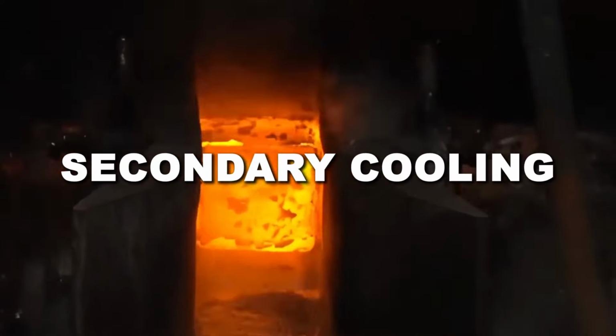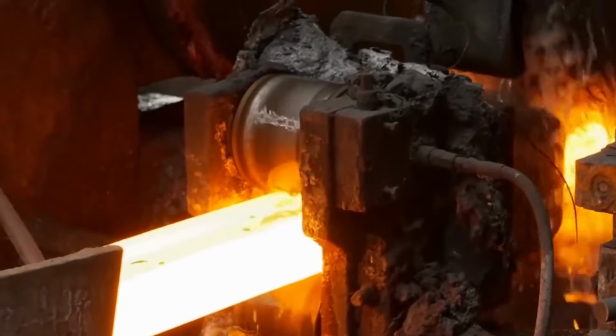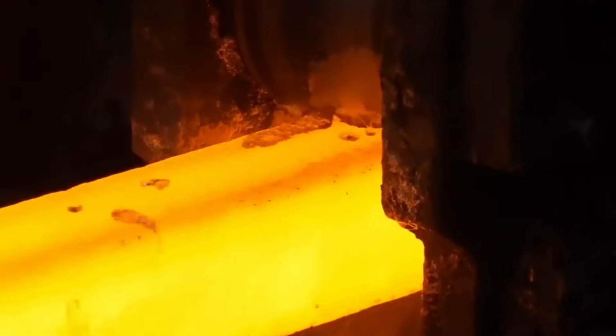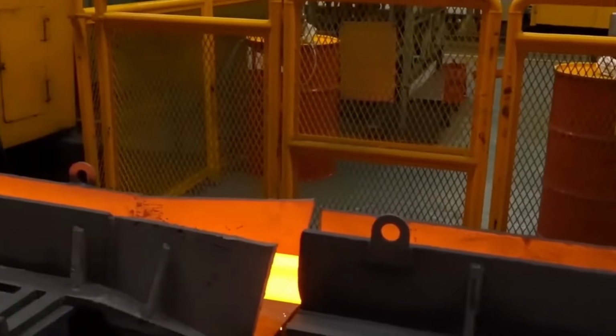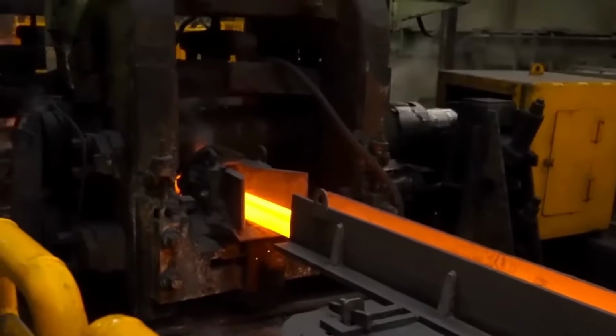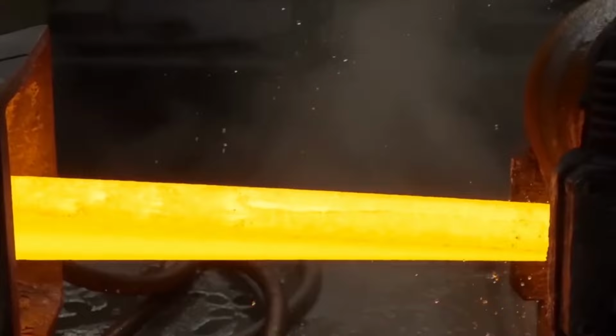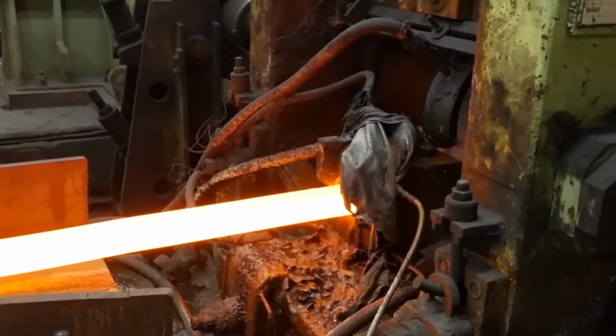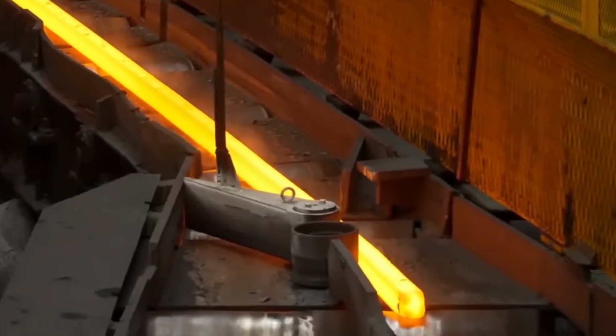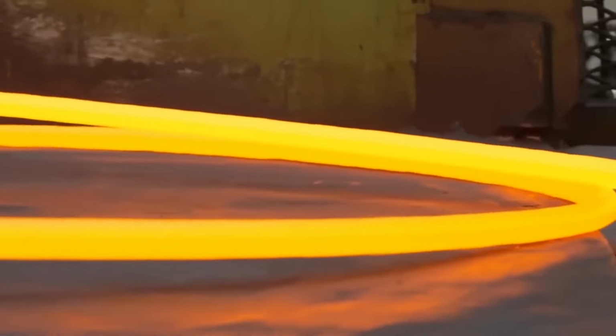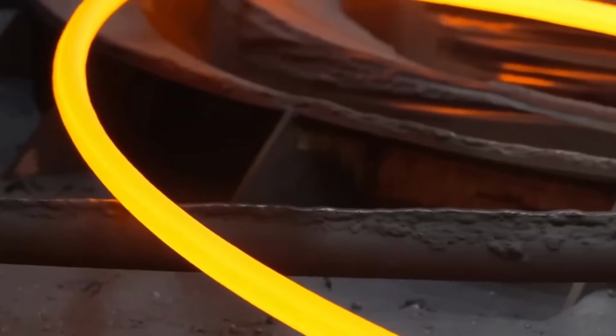Next comes secondary cooling. The newly cast steel moves along a controlled path, where it is sprayed with water or air to fully harden. The cooling process has to be just right. Too fast and the steel can crack, too slow and it won't be as strong. Once the steel has partially hardened, it is guided through massive rollers that help shape it further. These rollers are hydraulically controlled, applying enormous pressure to maintain uniform thickness and eliminate inconsistencies in the metal's structure.